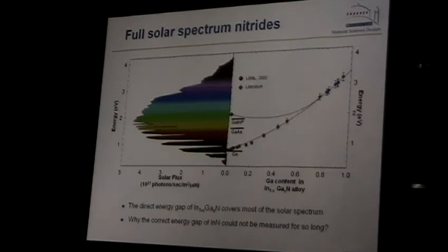Now when you compare it with the solar spectrum, it's obvious that this is a very interesting material because the solar spectrum extends from about 0.5 electron volt to close to 4 electron volts. And our material has a gap which changes from 0.7 to 3.4, which is a very good match. Because when you look at the current technology, germanium, gallium arsenide, and gallium phosphide, they only cover this range. In fact, there is a gap here, which people worry about. And they are already very efficient. So in our case, we can basically have any gap we want.